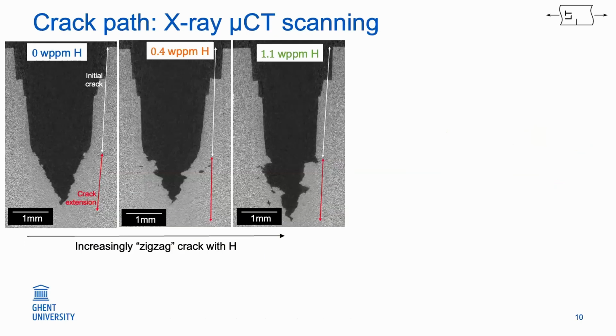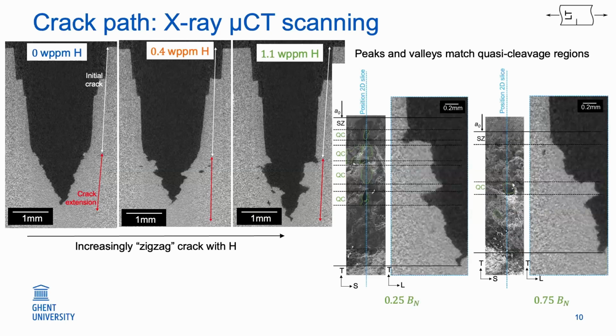Also, if we look at the CT scans, we can take a look at the shape of the crack path. And what happens with hydrogen is that this crack grows in a more jagged or more zigzag way. And if we link this to the fracture surface, we can see that those peaks and valleys in the zigzag crack path do correspond with regions of quasi-cleavage on the fracture surface. So clearly, the quasi-cleavage really participates in the crack growth.